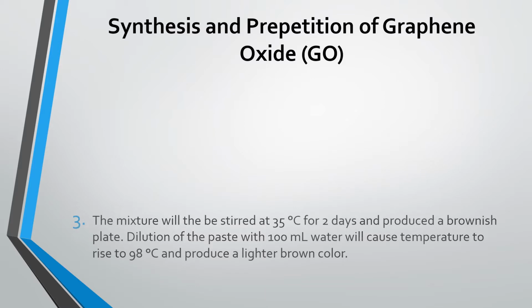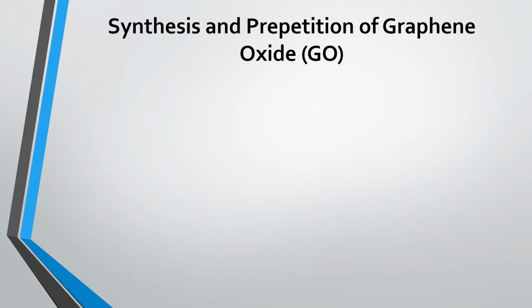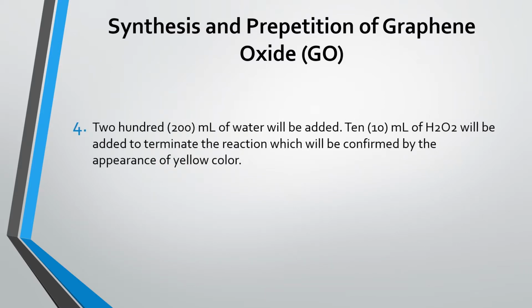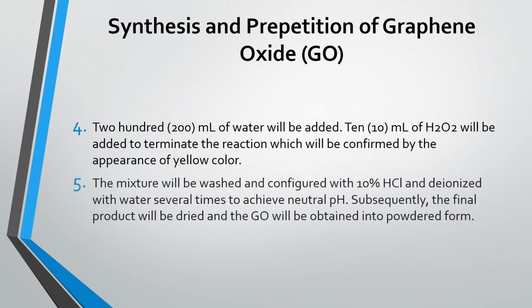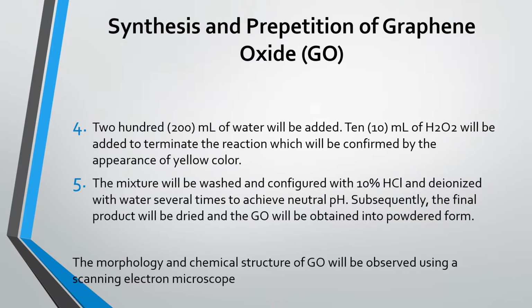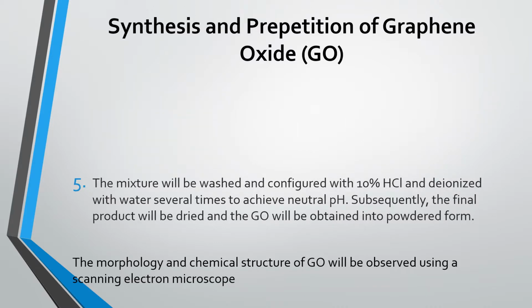10 ml of hydrogen peroxide will be added to terminate the reaction, which will be confirmed by the appearance of a yellow color. The mixture will be washed with 10% hydrochloric acid and deionized water several times to achieve neutral pH. Subsequently, the final product will be dried and the GO will be obtained in powdered form. The morphology and chemical structure of GO will be observed using a scanning electron microscope.